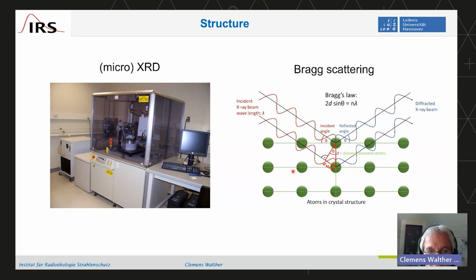Then if you're interested in the structure of the sample, you can use XRD, X-ray diffraction. So this is an example of a micro XRD. And here I just show you a sketch of how X-ray diffraction, Bragg scattering, works. You get an X-ray beam, have the diffraction pattern measured here, and that gives you some information on the distance between atomic layers. So you can get lattice distances, and if you do it a bit more advanced, you can do Laue scattering and get also information on angles of different layers and on the inverse lattice of the solid. So it would lead too far here, but even in very small samples, microns, you can get real good crystal information on your sample.